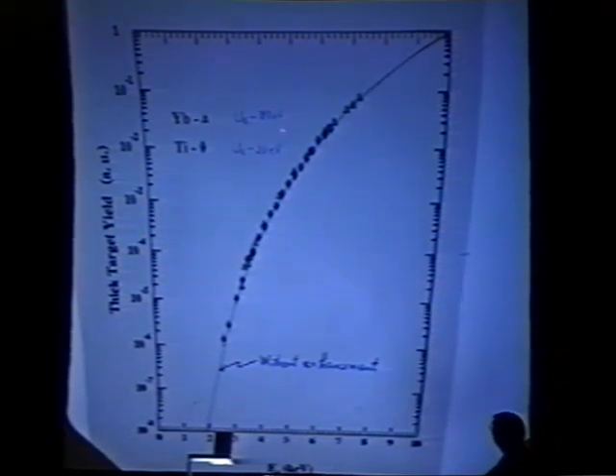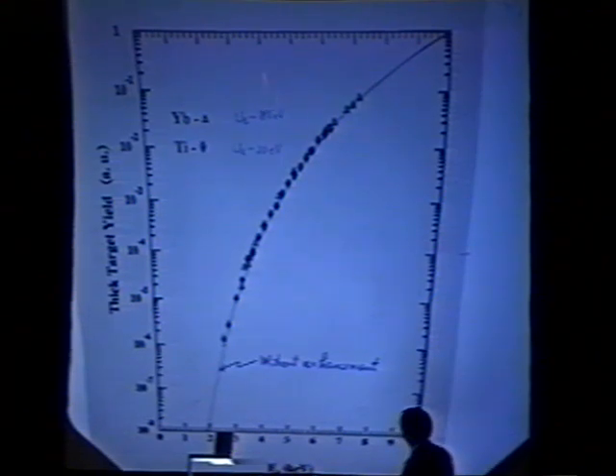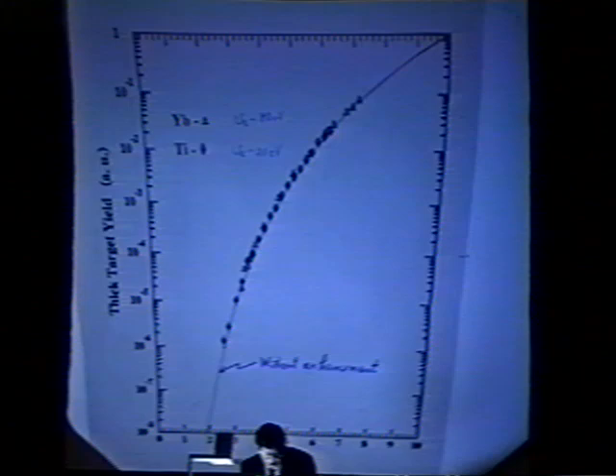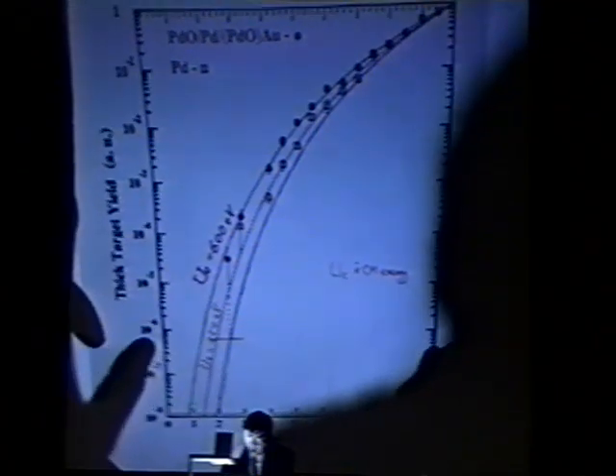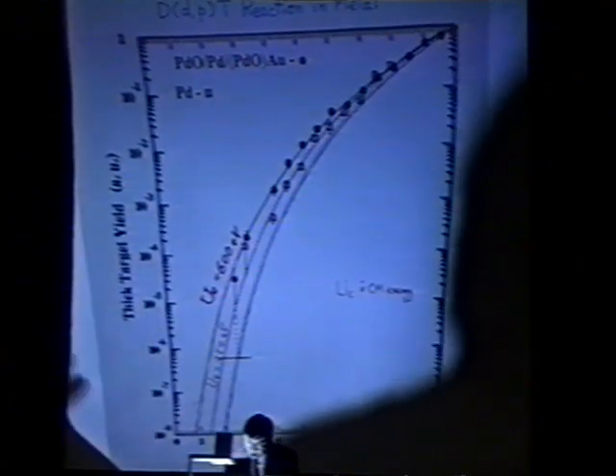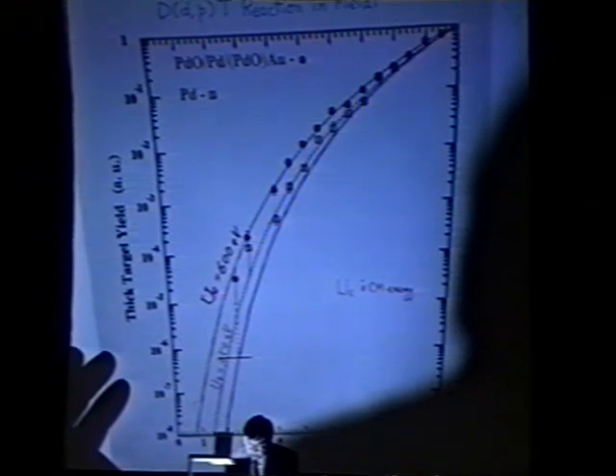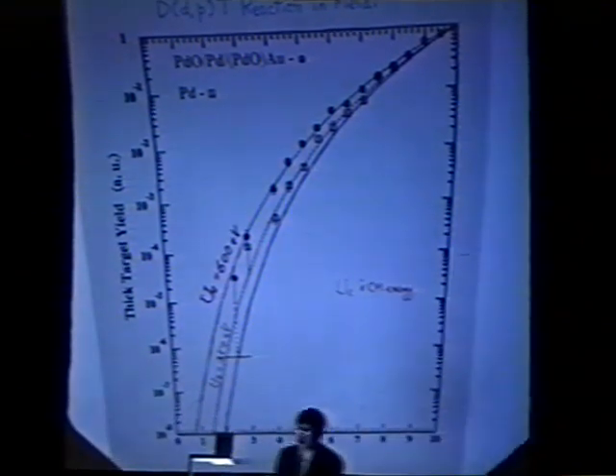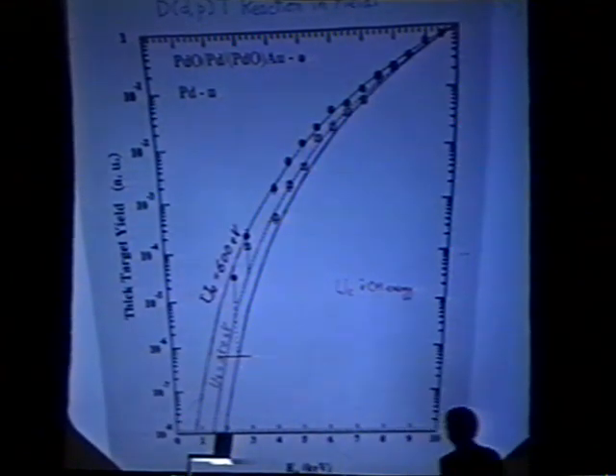For example, for the deuterium case, if we parameterize this enhancement as a screening potential, we got this value for deuterium in titanium, 20 eV for titanium. But for the palladium and the palladium oxide case, we have a very big enhancement.